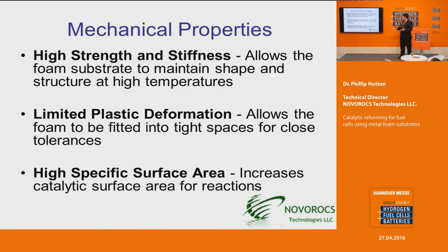Again, some of the properties of metallic foams. Typically, a metallic foam has high strength and high stiffness. This allows the foam to maintain its shape and structure throughout the temperature range up to 900 degrees Celsius, depending on the type of foam you're using. We can coat foams that are made from FeCrAlloy, which are high temperature metals that can withstand temperatures up to 1,000 degrees. But typically, we use either nickel metallic foam or stainless steel metallic foams.